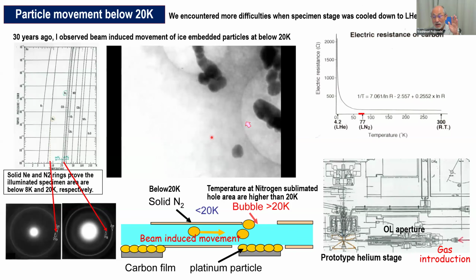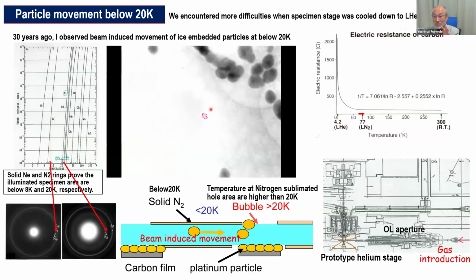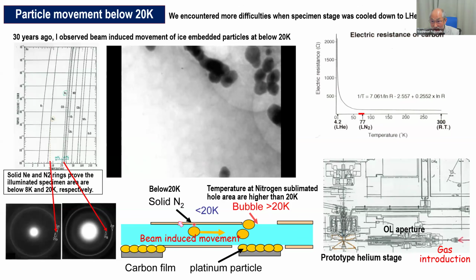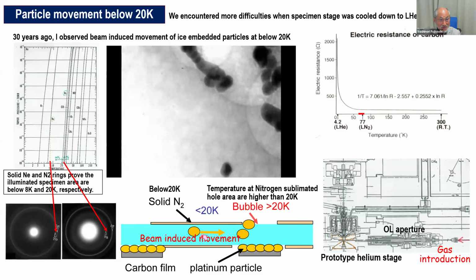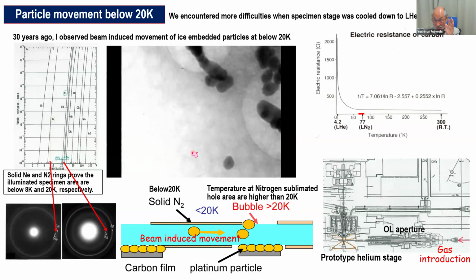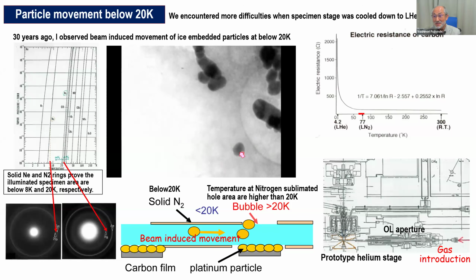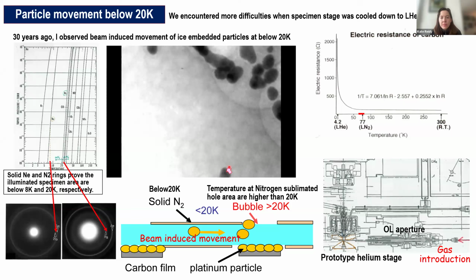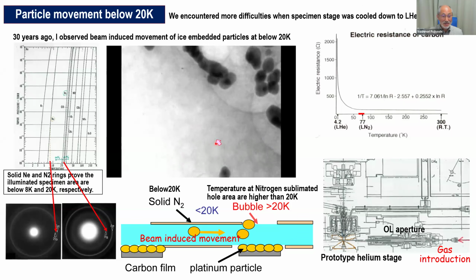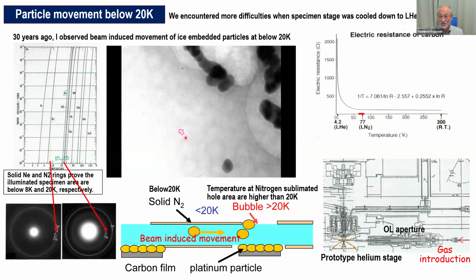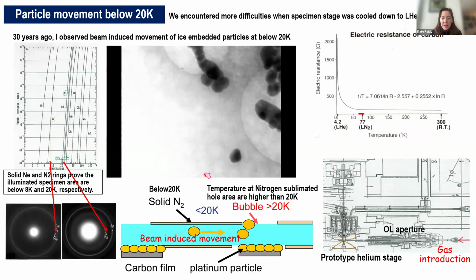I see. It means the solid nitrogen film disappears, meaning this part is below 20 Kelvin. So we confirmed the electron beam illuminated area is still below 20 Kelvin. And unfortunately, the platinum particles are moving around heavily. I don't know why, but anyway, we encounter this kind of serious problem when we use liquid helium. Interesting. So this was a liquid helium and gas flow stage that you designed.